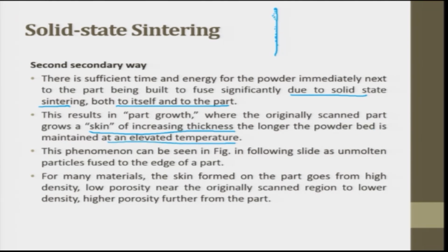So this is what they call a skin, which is getting stuck to the surface. This phenomenon can also be seen in the next figure, as an unmolten particle fused to the edge of the part. For many materials, this is the skin. The skin formed on the part goes from higher density, low porosity near the original scanning region to lower density, higher porosity further from the part.